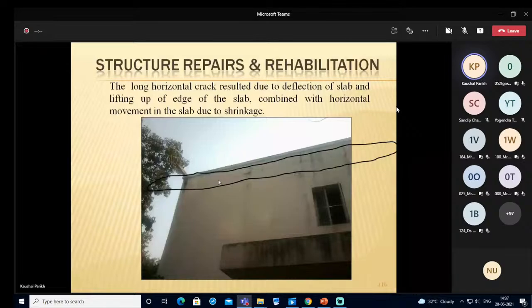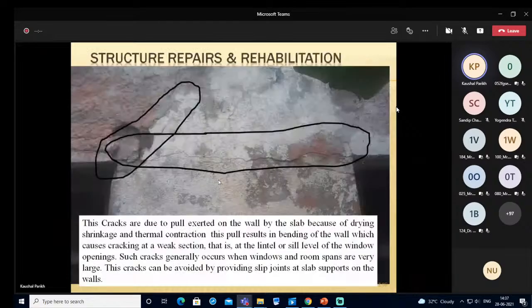This is nothing but the opening of doors or windows, where a crack can be visualized. These cracks are due to the pull exerted on the wall by the slab because of drying shrinkage and thermal contraction. This pull results in bending of the wall, which causes cracking at a weaker section, that is at the lintel or sill level of the window opening. Such cracks generally occur when the windows and room spans are very large. These cracks can be avoided by providing slip joints at the slab supports on the wall.